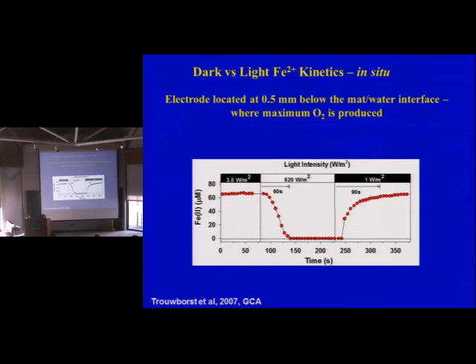Now the question becomes, okay, we're getting this precipitation of iron from dark to light, all right, with the cyanobacteria. The question is, how fast is that? So here's an example where we put the electrode at 0.5 millimeters, right where the oxygen max is, all right? And now what we're going to do is make it dark, and then we're going to make it light. Within 60 seconds, at a normal day, 620 watts per meter squared, today would be in that category, you could take out all the iron.